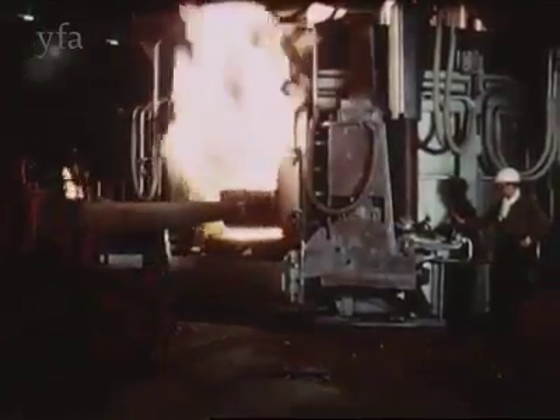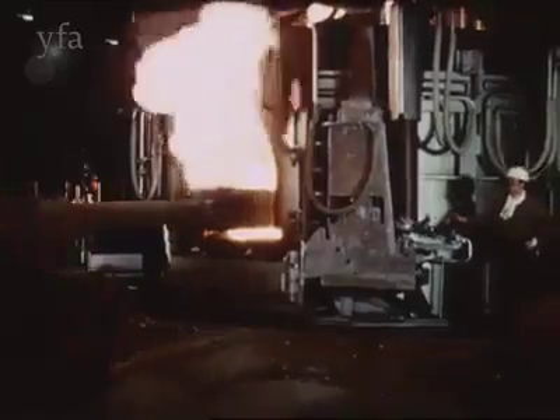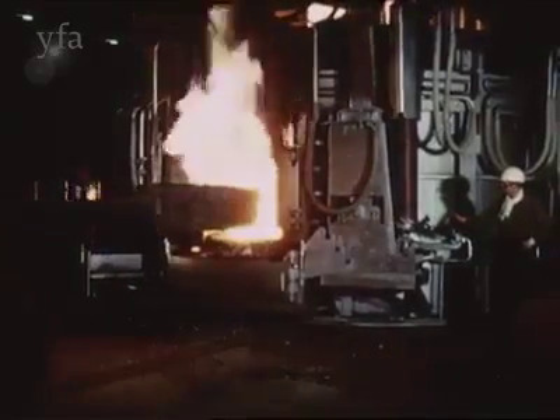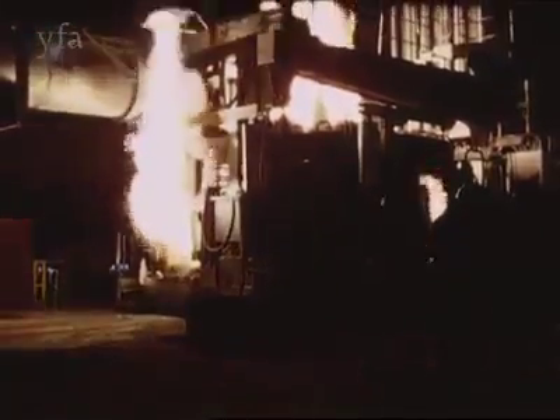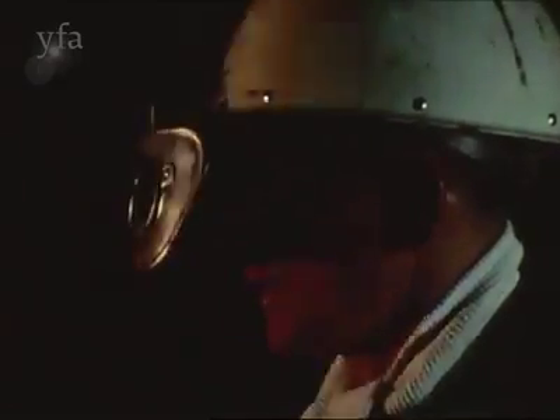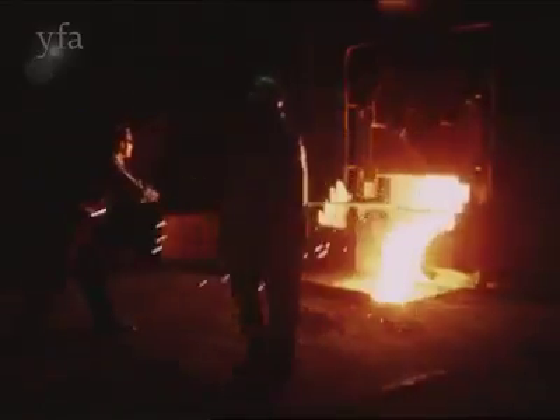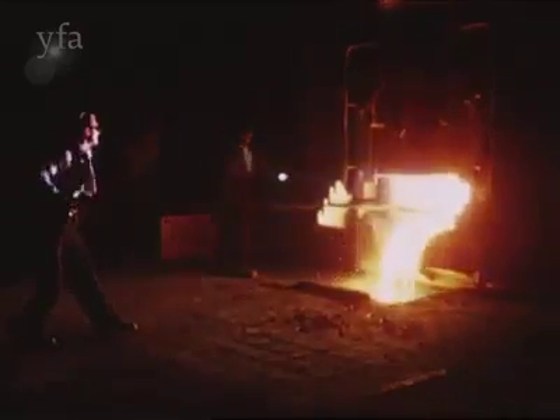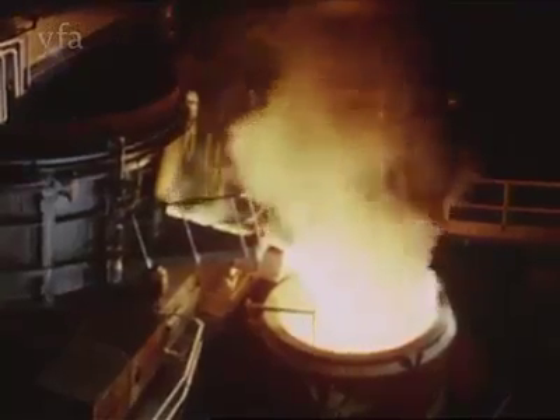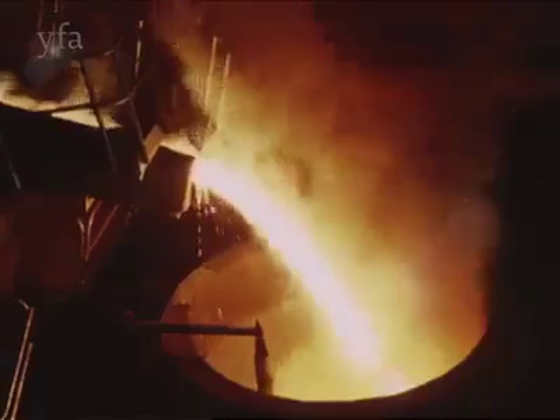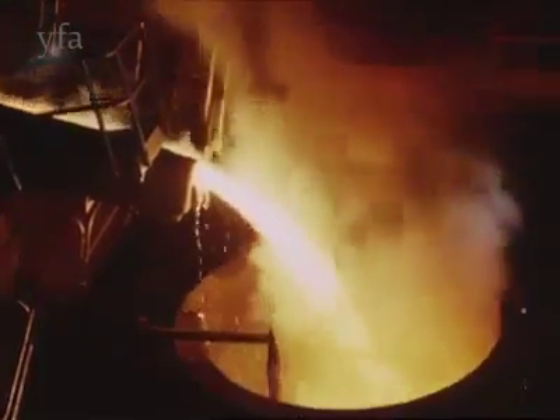Slag making additions are charged by means of a mobile charging machine. The furnace is slagged off, an operation which is repeated several times. The furnace is equipped with an induction stirrer which aids this operation and ensures uniform bath conditions. In addition to all the modern technical aids, a great deal depends on the skill and experience of the men operating the furnace. When ready for tapping, the furnace is tilted and the cast of over 90 tons of steel poured into the waiting ladle. The production cycle usually takes about 5 hours to complete.